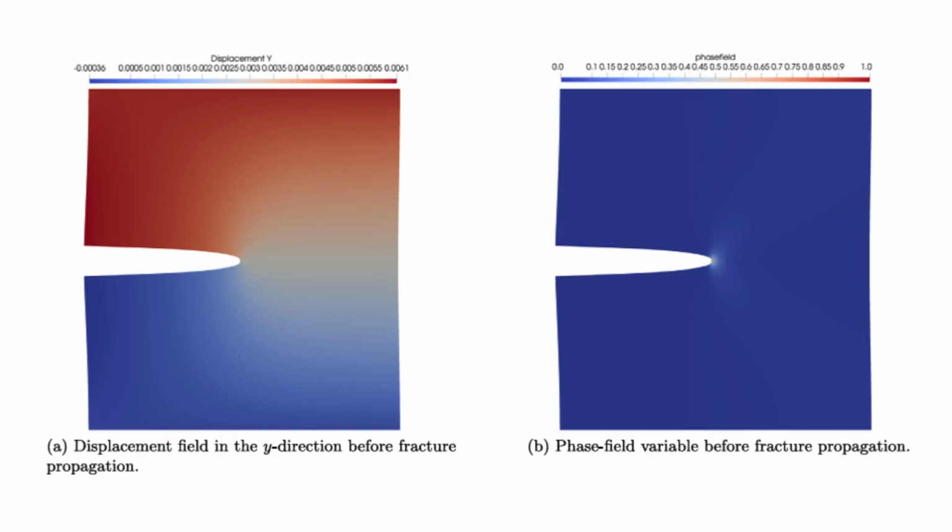And the result? Success. The simulation showed the crack growing just as expected from the notch, driven by tension, while the compression zone stayed intact. No non-physical crushing failures. That perfectly validates the need for that energy split, that decomposition we talked about. Without it, the simulation would have been garbage for this common scenario. Absolutely. It proved the implementation wasn't just mathematically sound, but also physically realistic under complex loading.